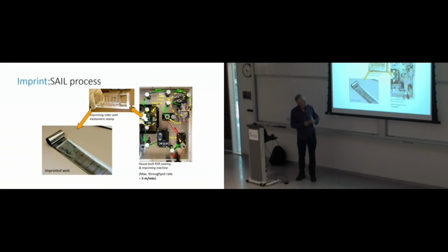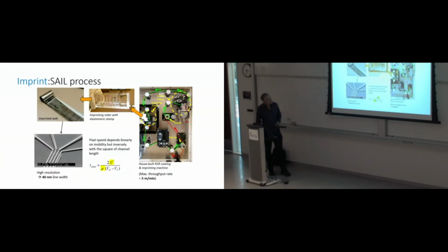And we did all kinds of things, so you don't even need this kind of equipment to do this in a university setting. You can just take your thing, make a PDMS master, and then use this bladder to squeeze stuff out from the center so you don't trap stuff in the middle. Or you can do a roller kind of thing. Some people put it on a roller and then just roll it out and do the imprint lithography there. And again, if you can do your alignment, then you can just treat it like a photoresist mask and do what you normally do. But it can be at nanometer type scales if you want. And you can do very precise height controls on things.